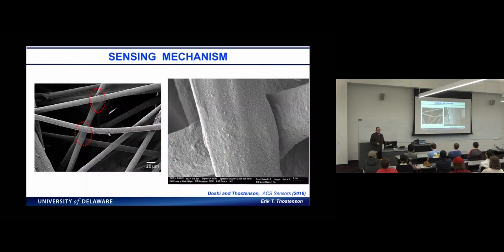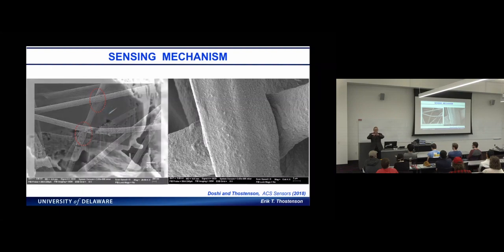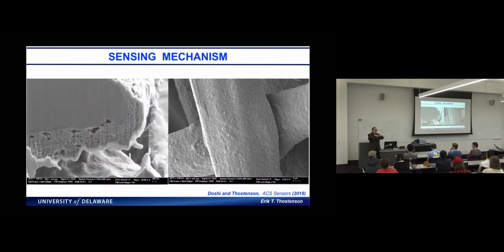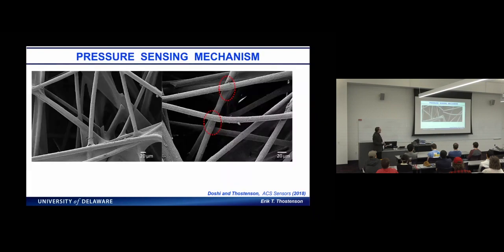And as I mentioned, you're compressing that foam-like interface, but also what happens, and why we use the aramid fabric, is that the strength transverse to the fiber direction is fairly low. So that causes the fibers to flatten out a little bit. So if we're using it as a very high pressure sensor, we have to preload it up to that range because there's a little bit of change from flattening out, but it's really that mechanism which gives us this huge range.